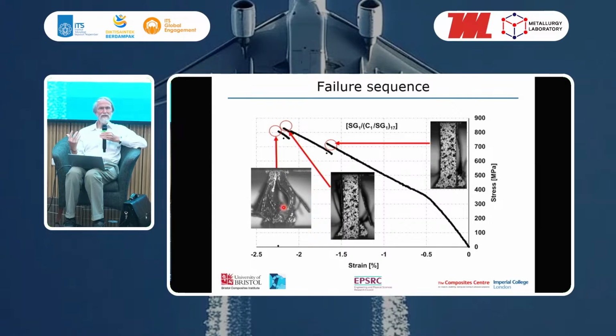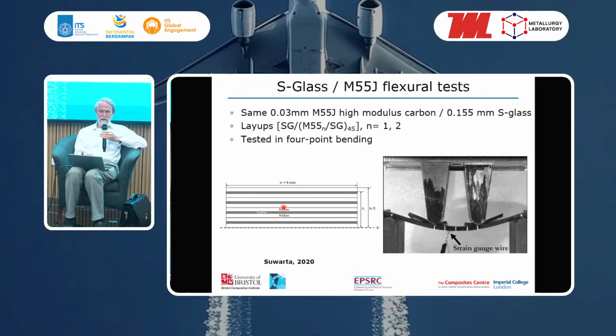Now what happens in bending? Bending is really interesting because we have tension and compression. One side of the specimen is in tension, one's in compression. We've looked at the pseudoductile behavior both in tension and compression, but in a bending test we'll get both of them. So that makes the behavior quite interesting. So the S-glass M55 tested in bending with this laminate where we have M55 and glass repeated through the thickness, and we've got here either 1 or 2 plies of M55 together, loaded in bending in the same 4-point bending rig.